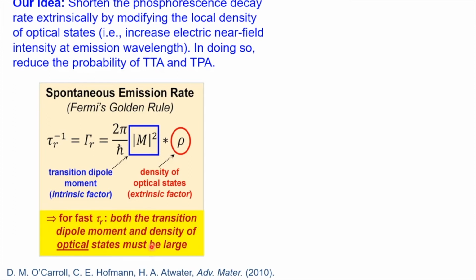And this idea comes from Fermi's golden rule, which states that the spontaneous emission rate of emission from a light source is proportional to the transition dipole moment of the material that's emitting light. That's an intrinsic factor to the material, as well as an extrinsic factor, which is the density of optical states. So for the most part, people will modify the transition dipole moment of the material by changing its molecular structure.